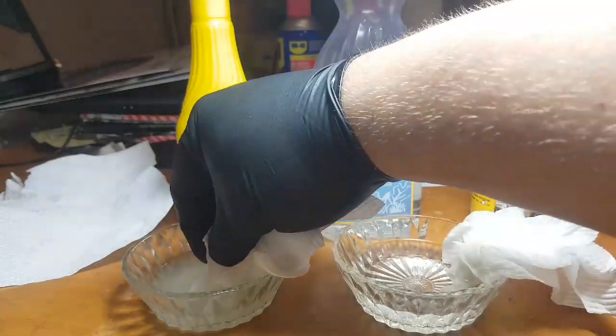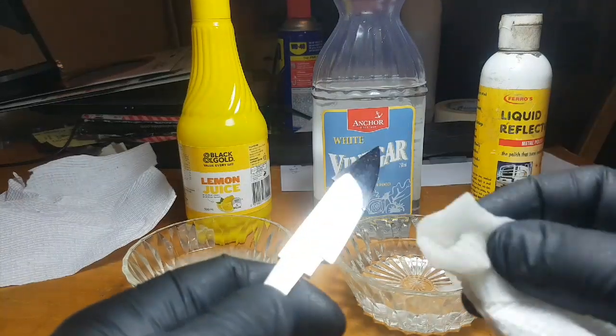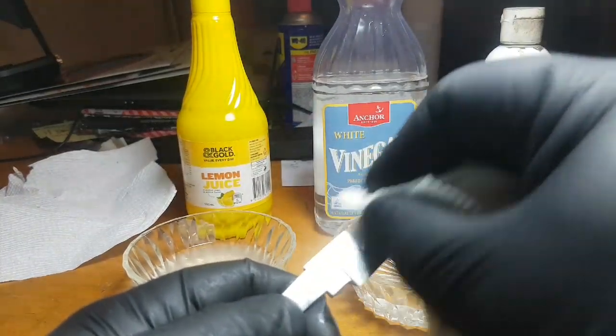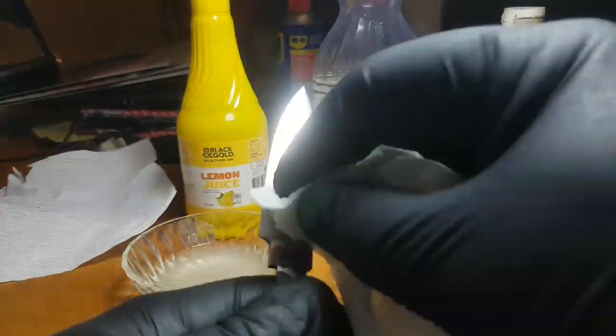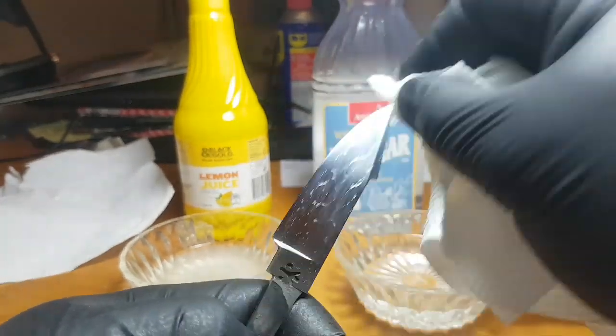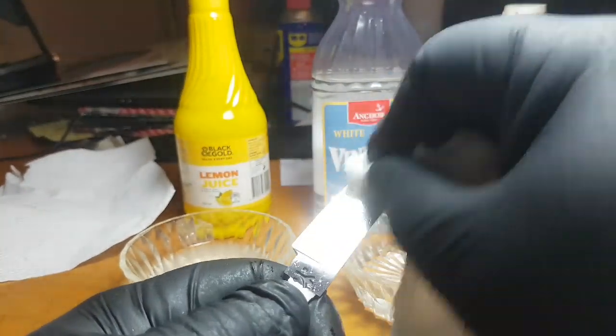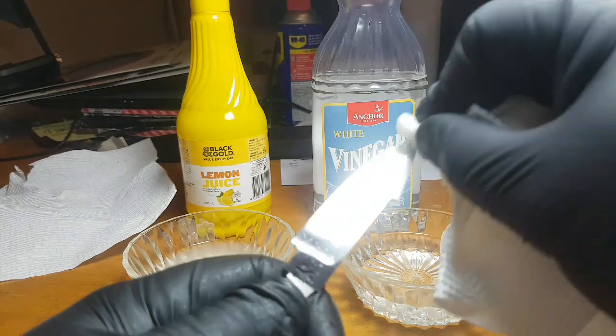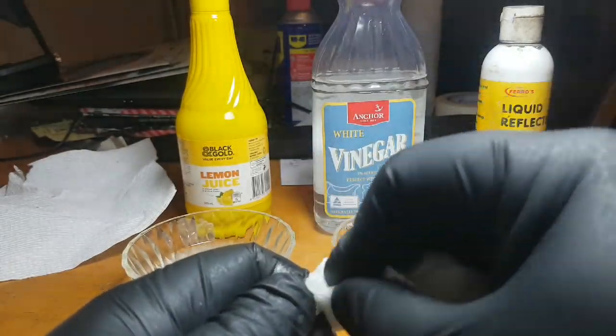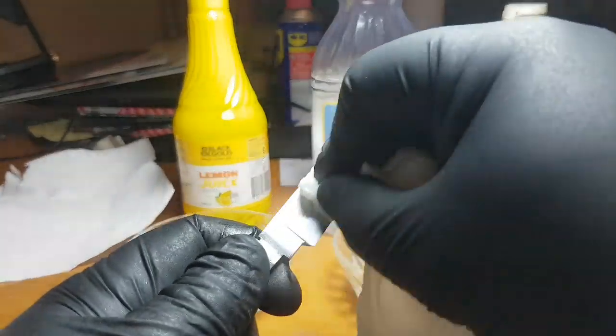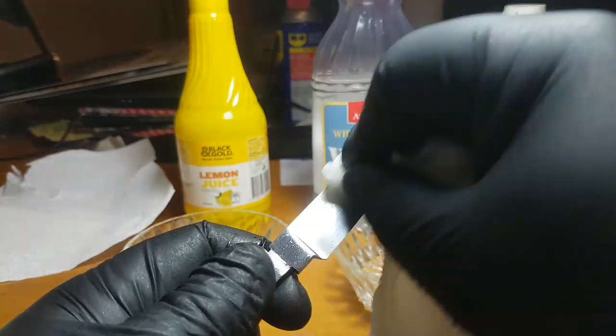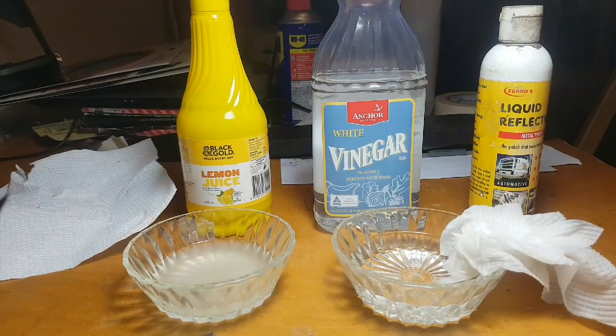And so I switch between the two, using vinegar until it starts to darken the blade, and then switching out from the vinegar to the lemon juice to darken out the blade. And you switch back and forth, and you'll start to see a significant change in the blade. Now, the higher polish you have, the longer this takes to happen. But if you continually rub, then you're removing slight surface oxides and continuing to get a nice, even, shallow edge.